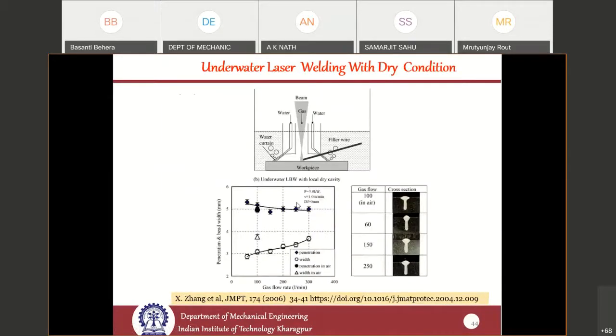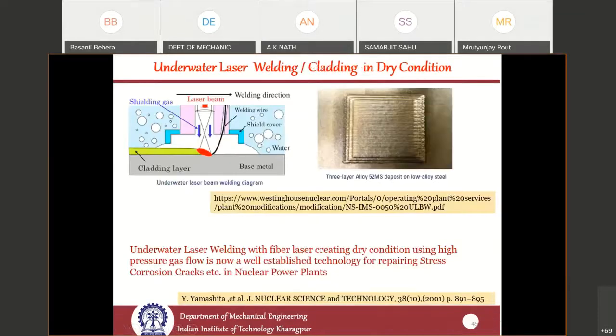Because of that, usually you do the welding by creating dry conditions, either by putting a water curtain and then high pressure gas jet, and then you can do power filler wire welding in thick material, and do welding underwater. This has been used in the nuclear industry, as I mentioned earlier, and here they have tried to do cladding by wire deposition as well as wire-fed welding of thick material up to 10 millimeters thick by making a V groove and then realizing the welding.